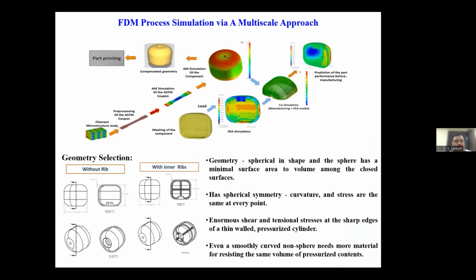So during the design and developmental aspects, we were able to identify how the cylinder can be strengthened. There are two ways associated with it: by providing new support structures within the cylinder, or by increasing the layer thickness of the cylinder. Increasing the layer thickness is not a viable option, because that involves a lot of polymeric material, and the thickness of the liner material eventually increases. With the increase in the thickness of the liner material, the weight of the cylinder also gradually increases. So in order to counterbalance the weight and the number of layers associated with the thickness, we introduced some kinds of rib-like structures within the cylinder.